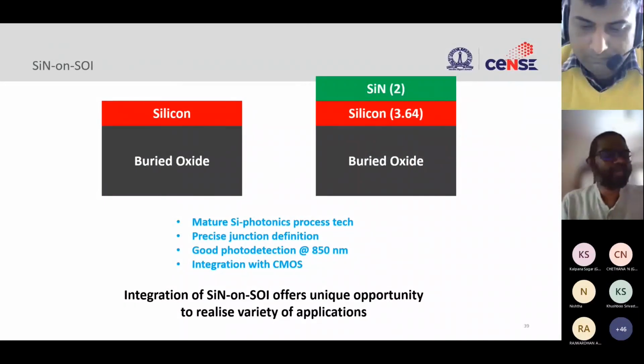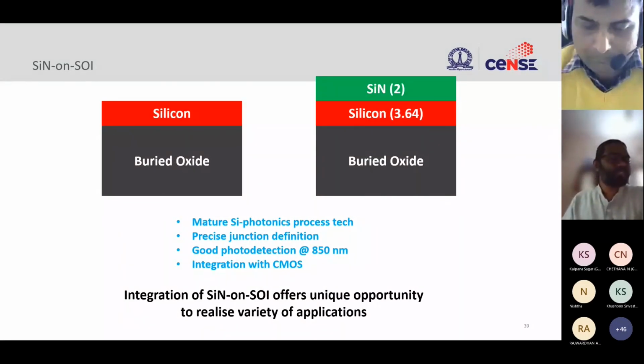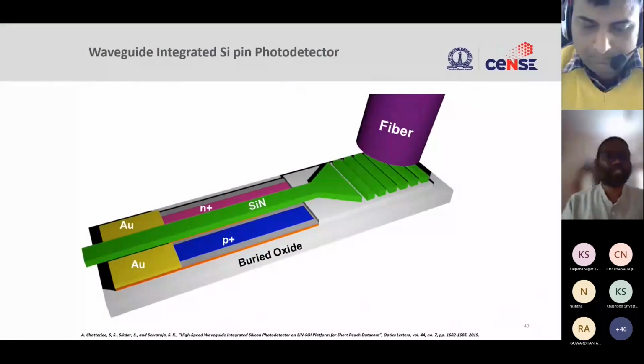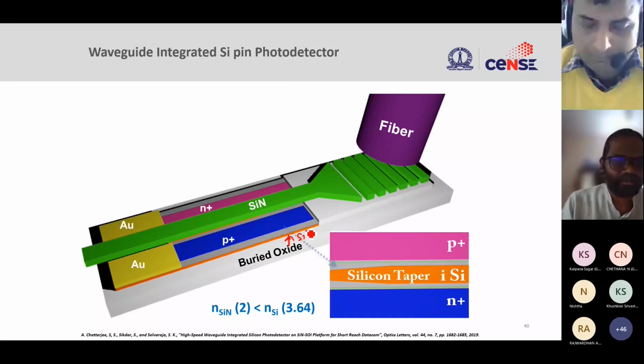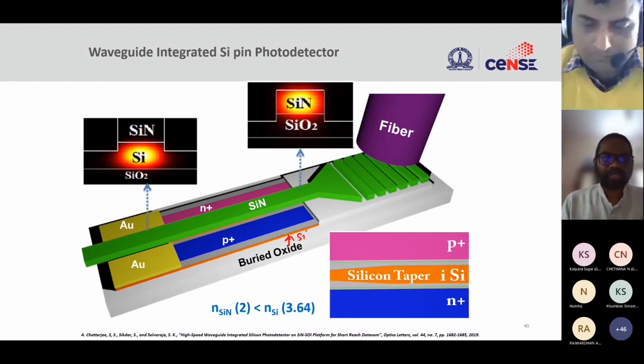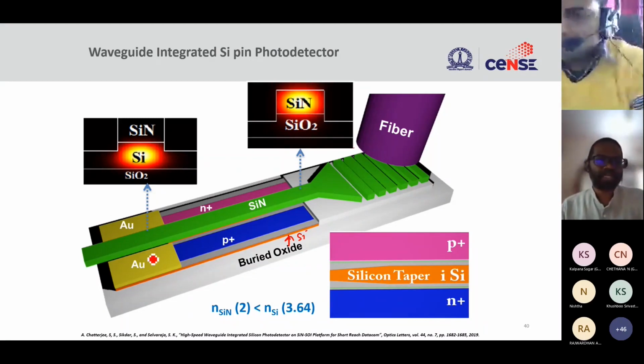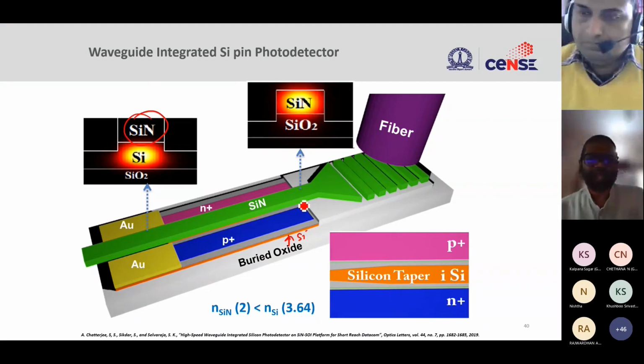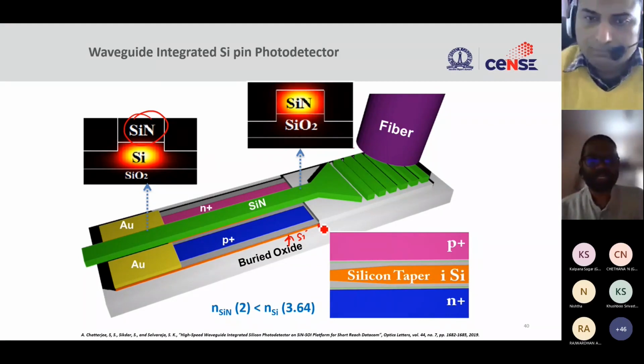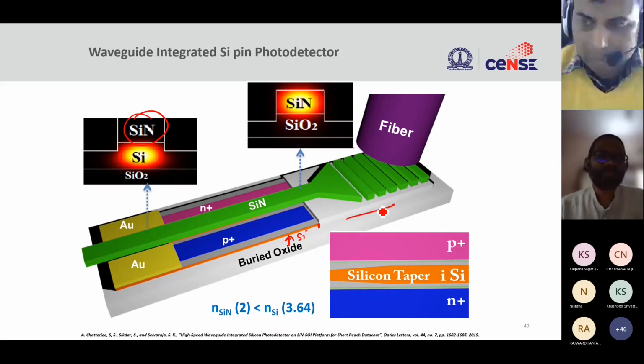So silicon, as we know, is a reasonably well-known material, but then we want to integrate it with silicon nitride. I said silicon nitride is the waveguide platform that we are going to use. So we thought we will take a silicon on insulator platform, and then put silicon nitride on top of it. So this is the circuit that we came up with. We have a very nice silicon circuit. What you see here is silicon sitting underneath, and silicon nitride is sitting on top. And in this location, we have removed the silicon. From here on, there is no silicon. And this is what we use for coupling.